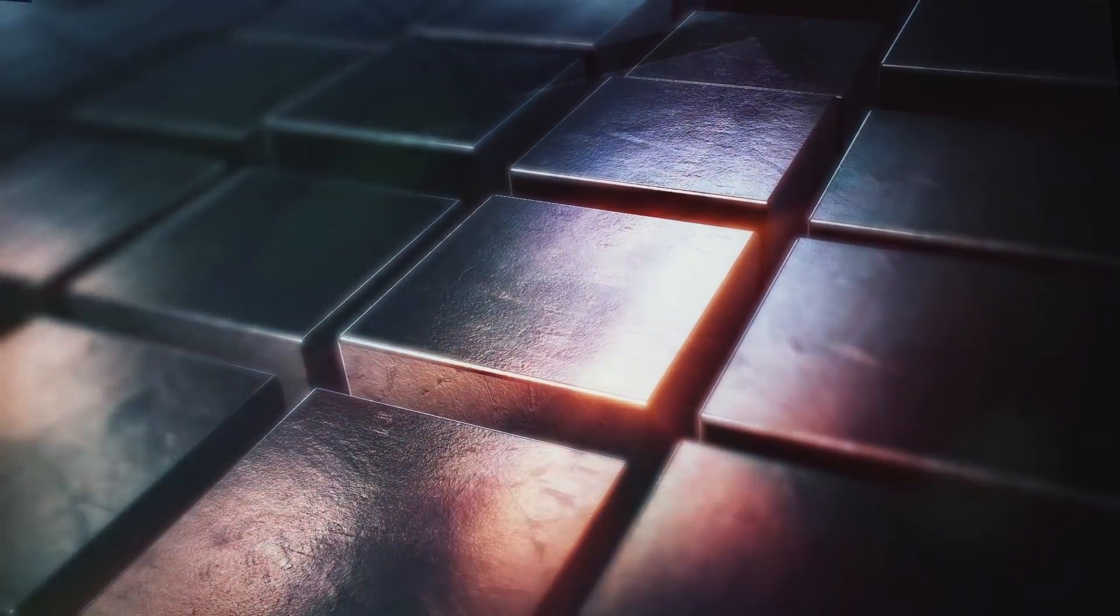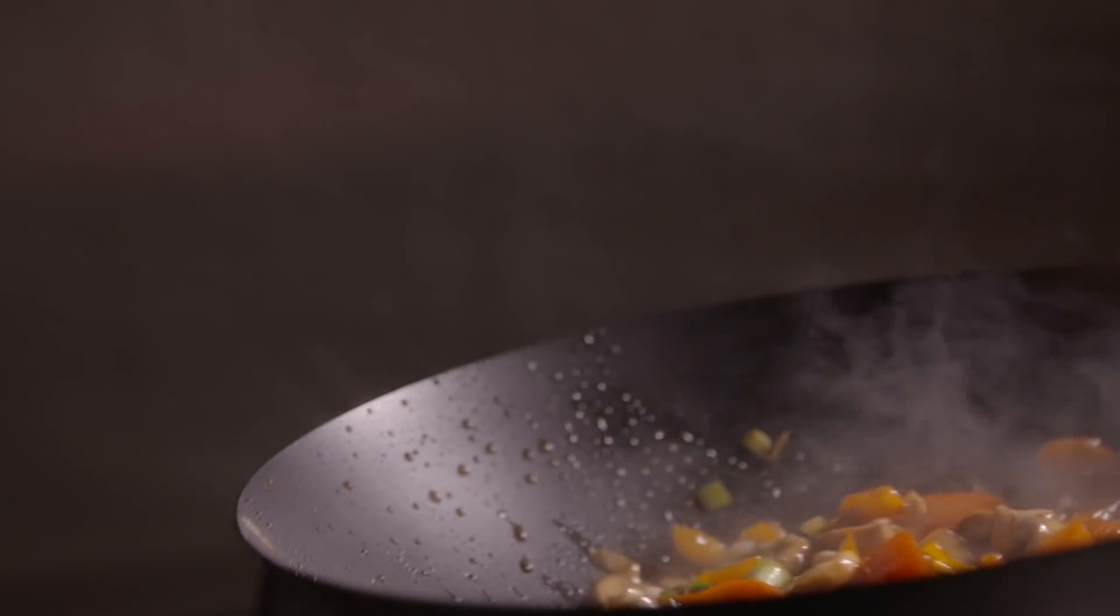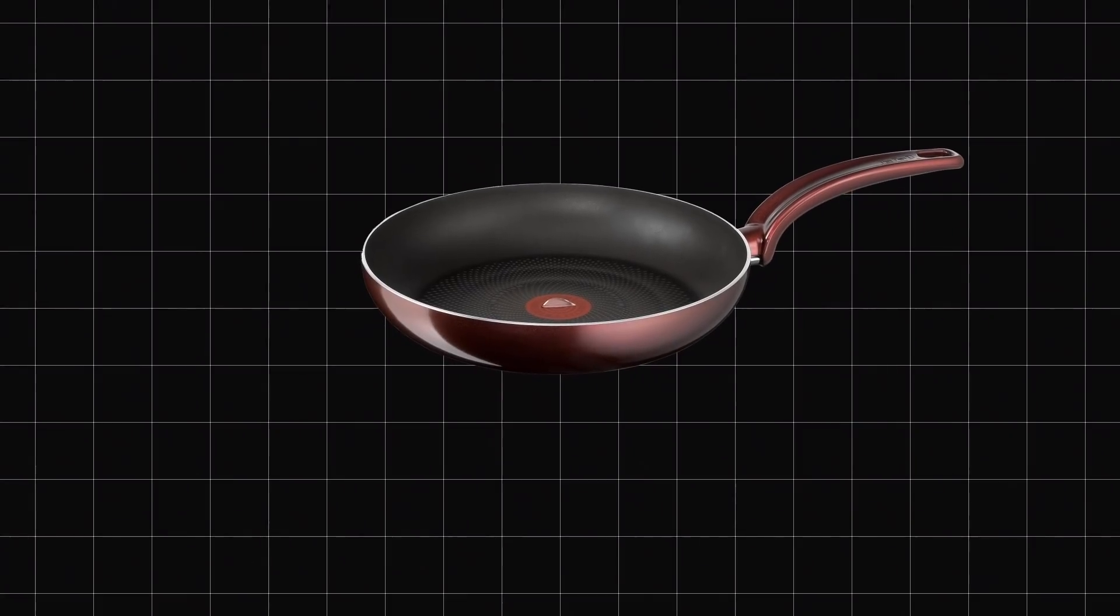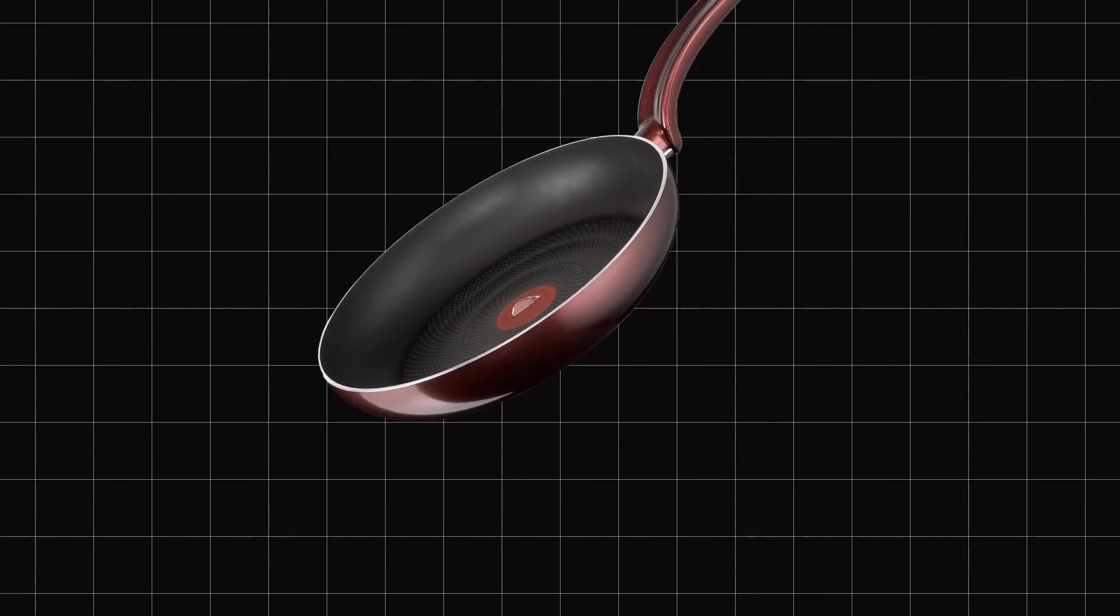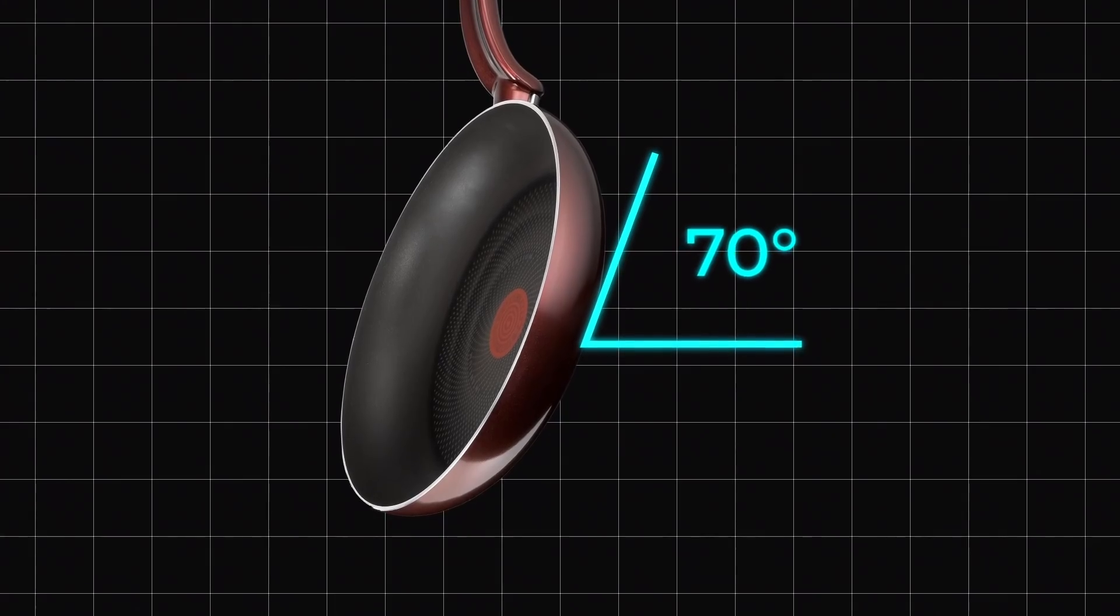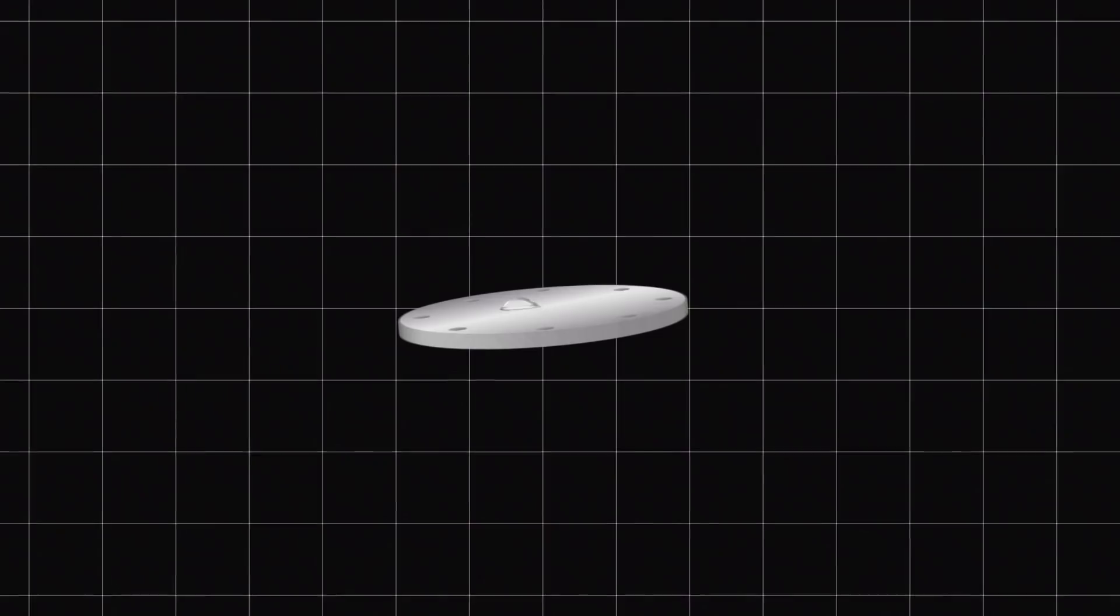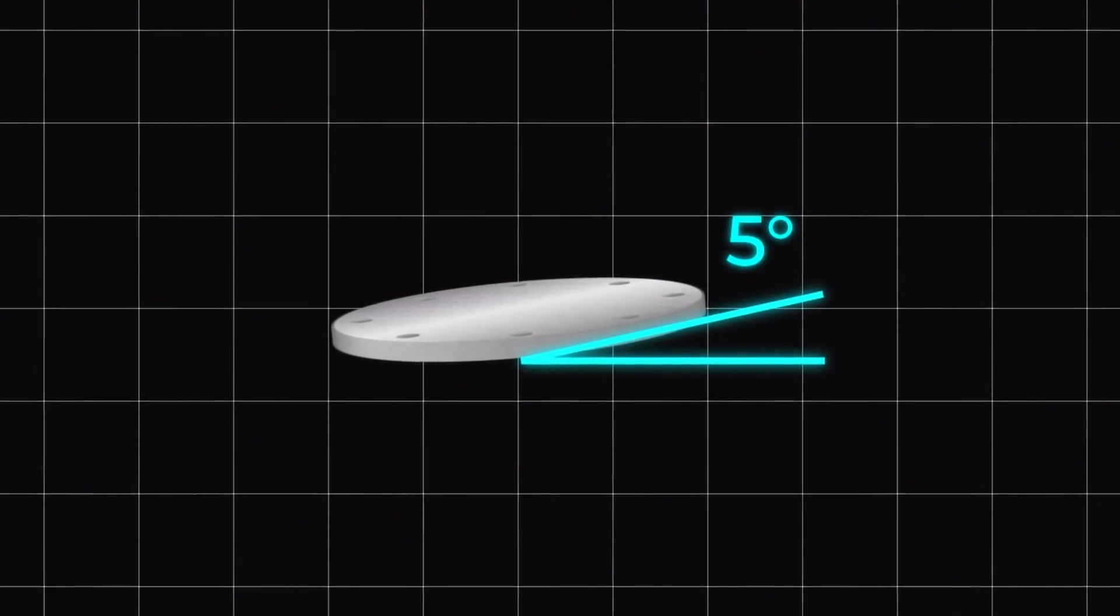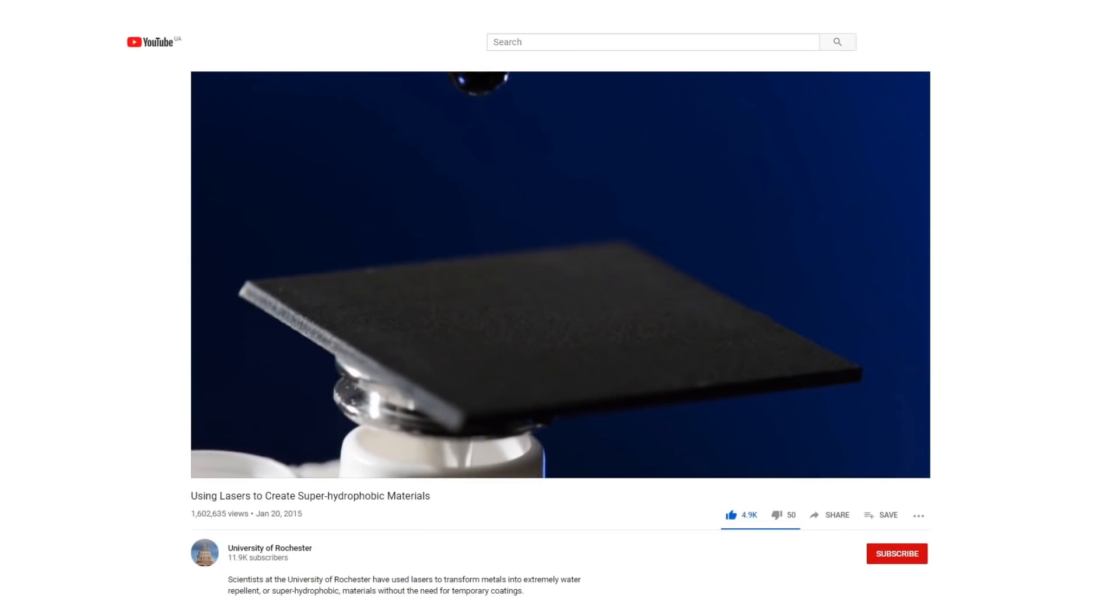The metals developed in laboratory are much slipperier than Teflon, which you probably know is a hydrophobic coating that is often applied to non-stick pans. In order for the water to slide off the Teflon surface, it must be tilted by almost 70 degrees before the water begins to slip. With metal treated with a femtosecond laser, water will slide off even when tilted by less than 5 degrees. The material is so strongly water-repellent, the water actually gets bounced off.